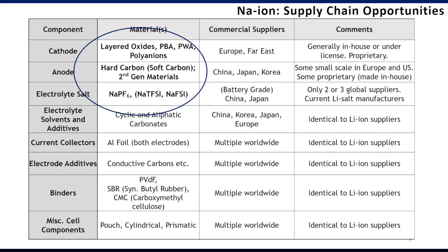Electrolyte salts, pretty well everyone is using NaPF6, and there are only two or three global suppliers of battery grade NaPF6 in the world. If you use non-battery grade, then you get all kinds of other issues in terms of insolubles. So I think there's an obvious requirement for more companies to enter the supply chain for things like NaPF6. And I'd also add that we need alternative salts to NaPF6. I've got in parentheses on the left-hand side these imide salts, the equivalent to what is available in the lithium space, so TFSI and FSI. Why those are in parentheses is because you can't generally use those with the layered oxide materials, because at the high voltages that these cathode materials operate at, you get problems with the corrosion of the aluminum current collector. So there's a problem there.